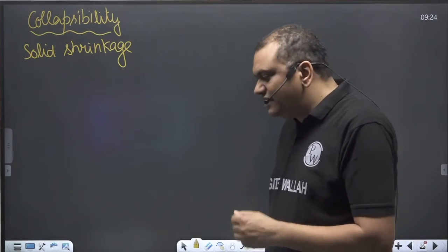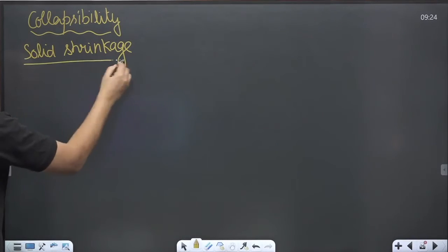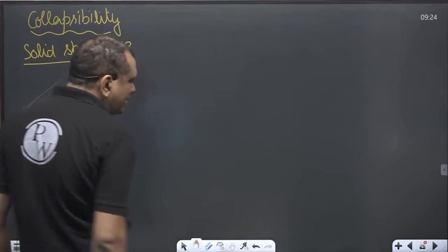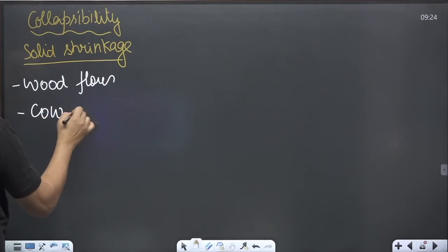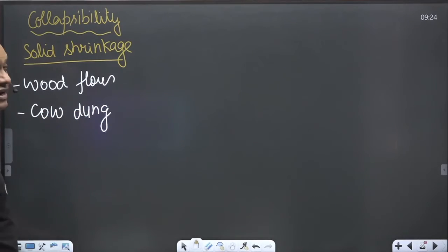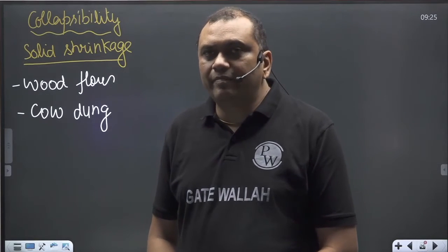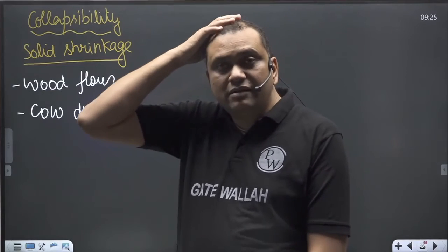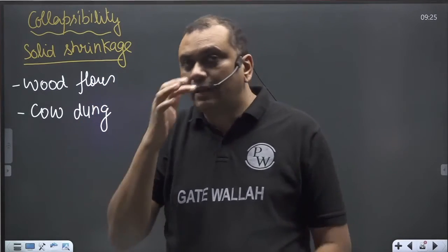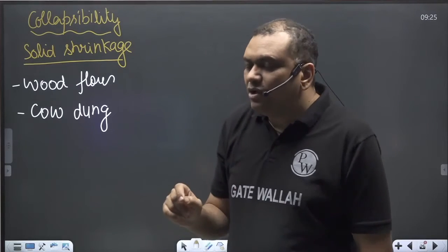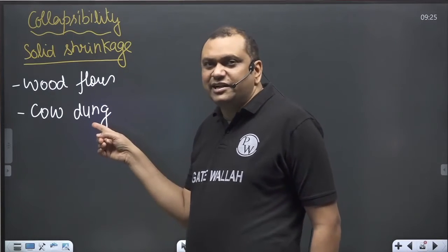So how exactly do we increase the collapsibility in the sand? We add some additives like wood flour or cow dung, around 3%. So what happens when you are pouring the liquid metal? Liquid metal will be hot. So hot metal will burn these additives,